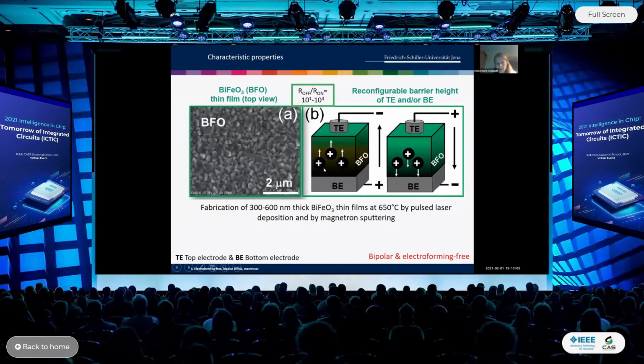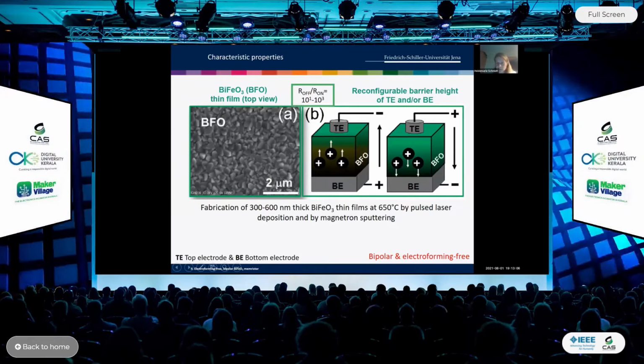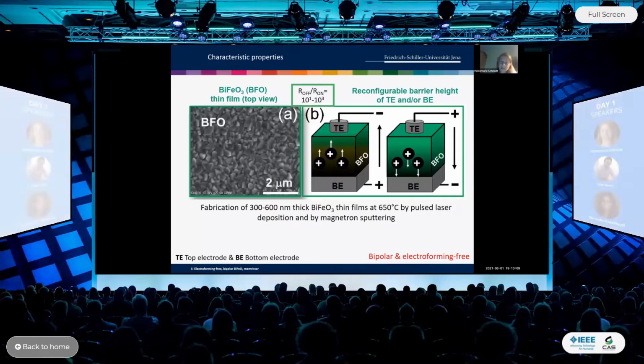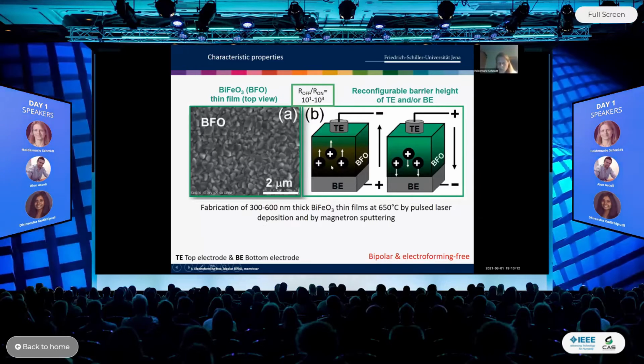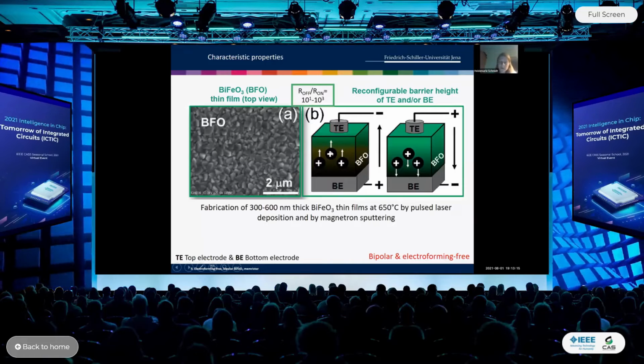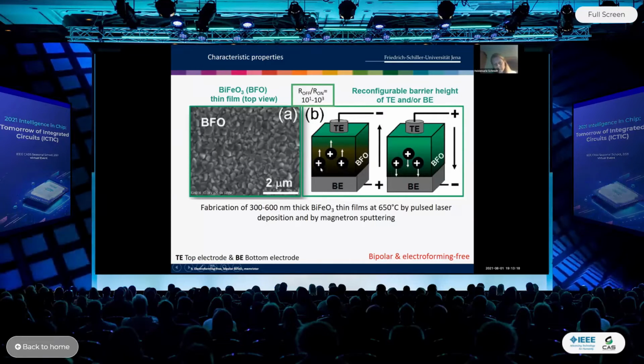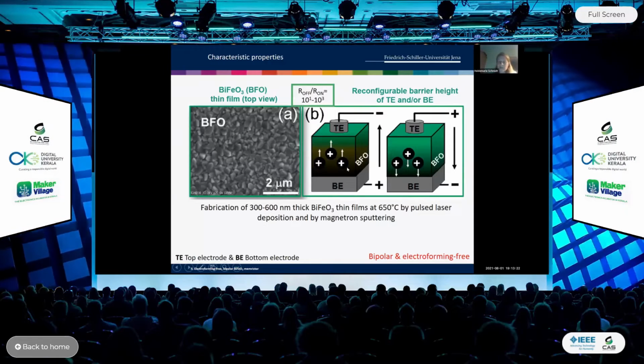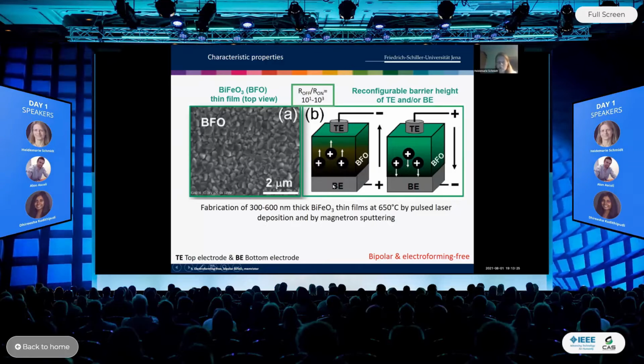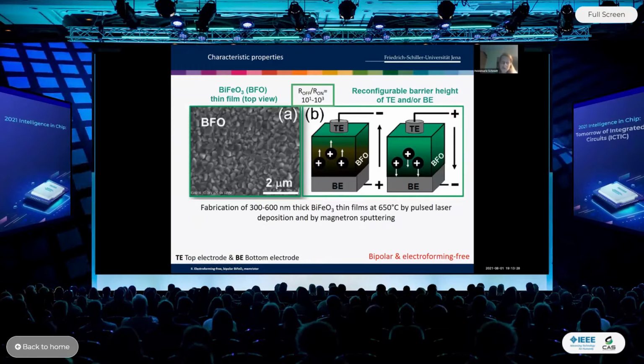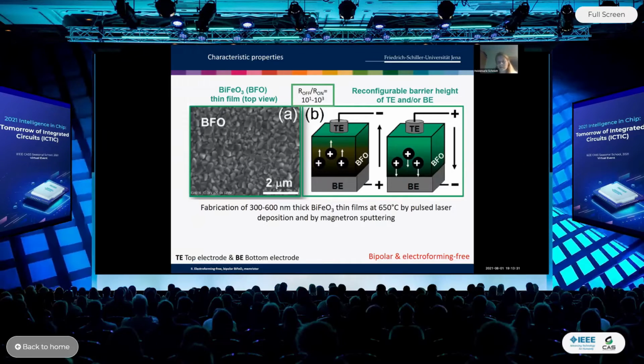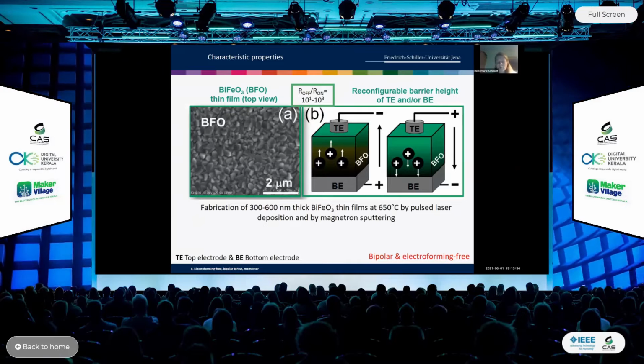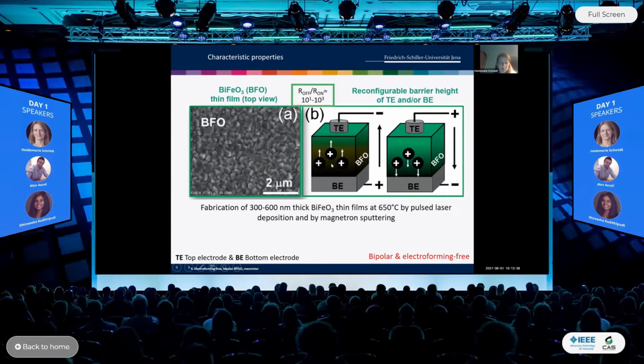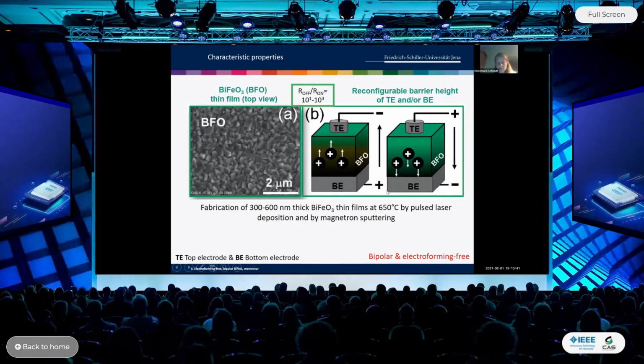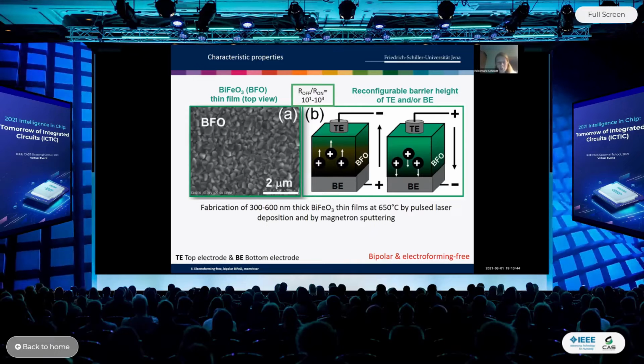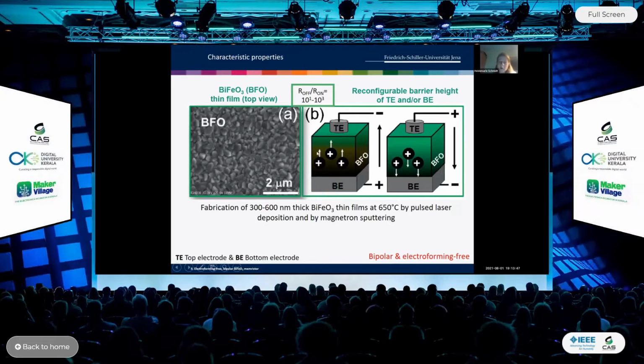It's a trap. This titanium is a trap, incorporated in the bismuth iron oxide host lattice. And what is this titanium a trap for? It's a trap for the oxygen vacancies which are present in this oxide material. It's n-type conducting, right? And those oxygen vacancies are mobile if the electric field between top and bottom electrode is large enough. If the electric field is very small, for example the electric field related to the reading bias, the readout bias, then they will not drift, because the drift velocity of such ions increases exponentially with the electric field. And if the electric field is small, nothing will happen. The oxygen vacancies will not be redistributed.